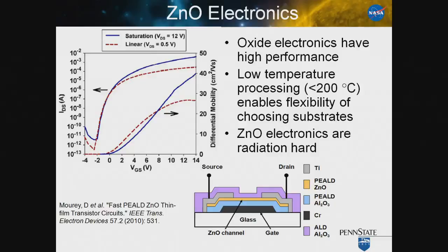There we go. This shows the functional electrical performance of such a zinc oxide thin film transistor on a glass substrate. You can see here excellent on-off ratios, so we're able to modulate the current by many orders of magnitude. The differential mobilities are on the order of 20 centimeters squared per volt second, and crucially, all of the processing is done at less than 200 degrees C. So we have at least a 300 degrees C window between the processing temperature of the piezoelectric and the processing temperature of the electronics. So we would not, in principle, expect the deposition of the electronics to degrade the underlying actuators.